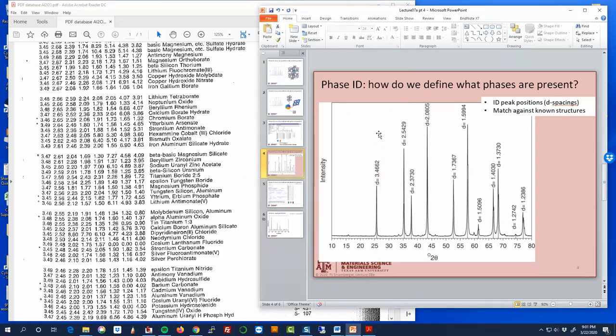That's important, because if you just have a good overlap between one or two, but there are a bunch of peaks that aren't explained, then what you're probably looking at is a combination of a few different phases. What we can tell from here is that this particular phase hits all of them, and there are no diffraction peaks we would expect to see in aluminum oxide that we don't see in our diffraction spectrum. That's the important thing.